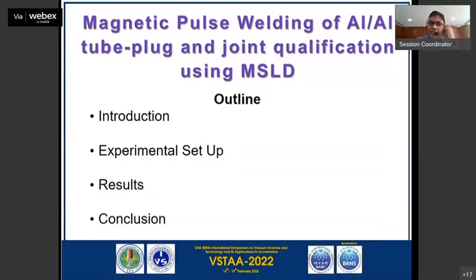Coming to my title, I'll first explain my title. What is welding? Welding is the process of joining two metals by application of heat or pressure or filler materials, or any combination of these. Here we are in magnetic pulse welding. It is pressure welding, whereby we apply the pressure using magnetic force in the form of Lorentz force. And it is pulsed, because we apply the pressure in the duration of microseconds, thereby the name magnetic pulse welding. Here we are trying to establish magnetic pulse welding for aluminium and aluminium combination.